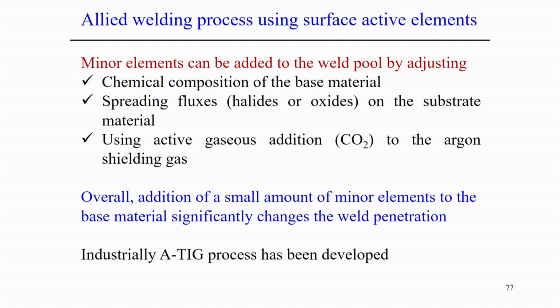And there is another way, directly using these surface active elements with the shielding gas. For example, sometimes carbon dioxide gas, CO2, can be used with the argon shielding gas, and here the oxygen can act as a surface active element to alter the shape and size of the weld pool. But overall, addition of a small amount of the minor elements to the base material significantly changes the weld penetration. So, based on these three different ways, we can add the surface active elements.